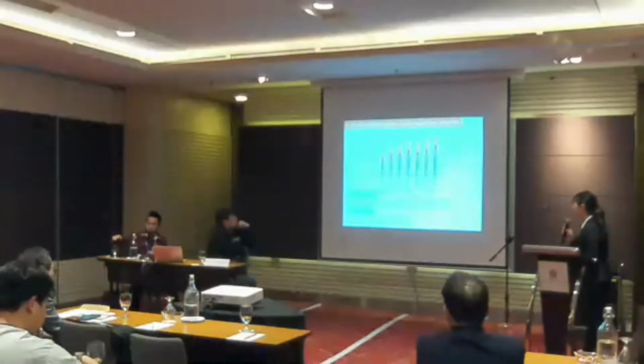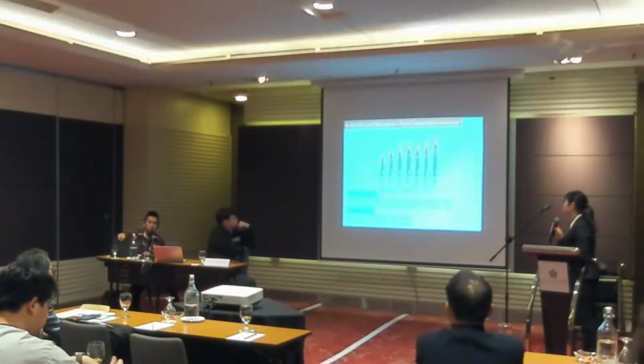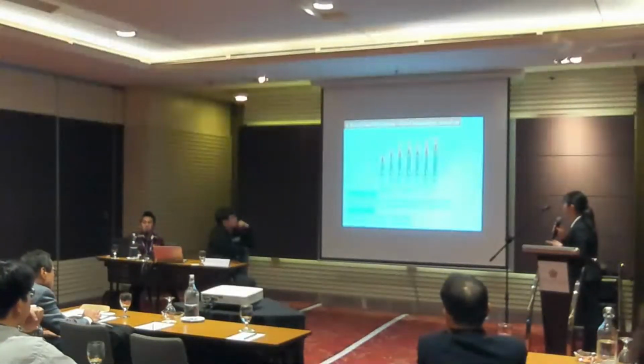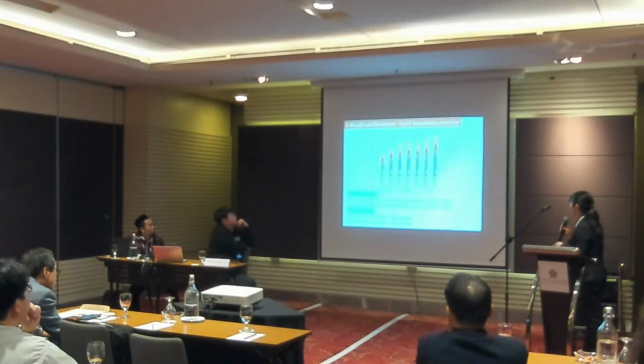This figure shows the gas composition of the actual tar. In olivine, the gas composition has the same trend as gas carbon, but CaO did not have the same trend as gas carbon. So syngas volume at 800 degrees Celsius was the same for CaO and olivine, but at 900 degrees Celsius, it was largest in CaO.